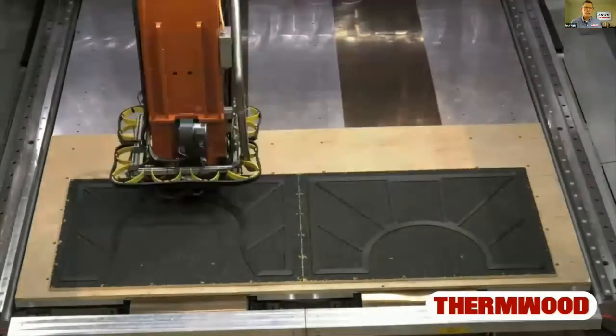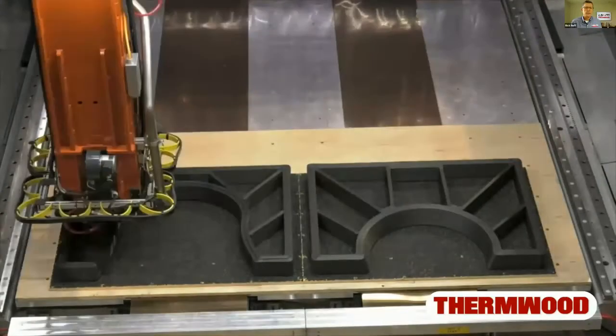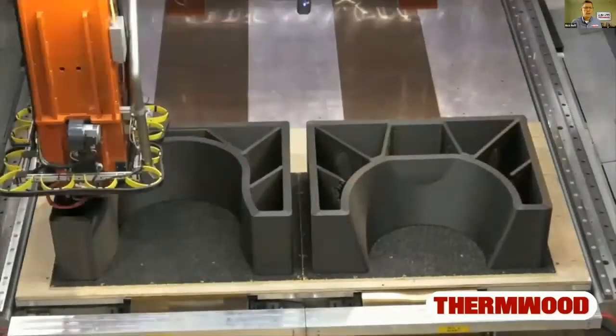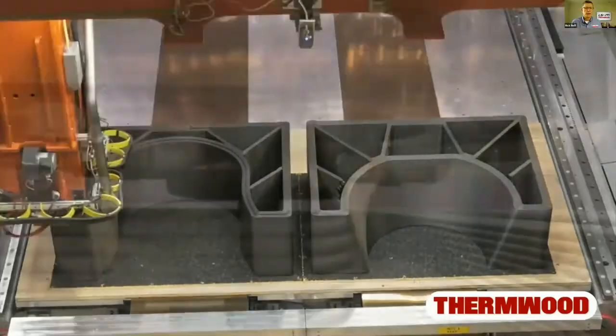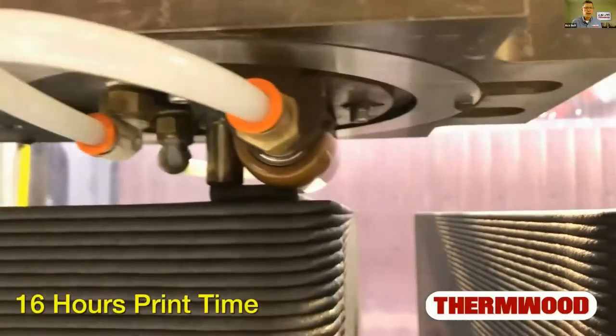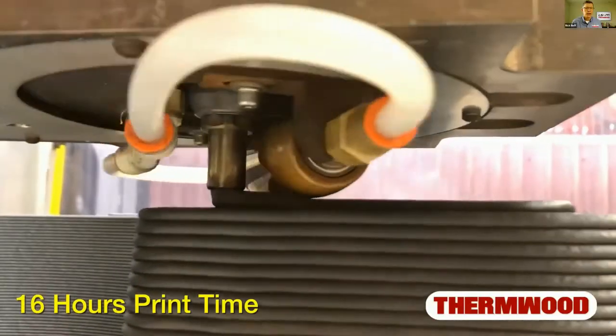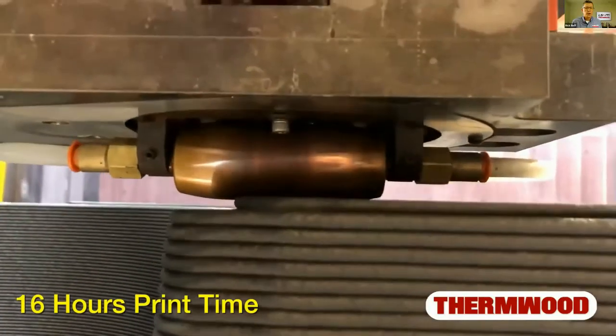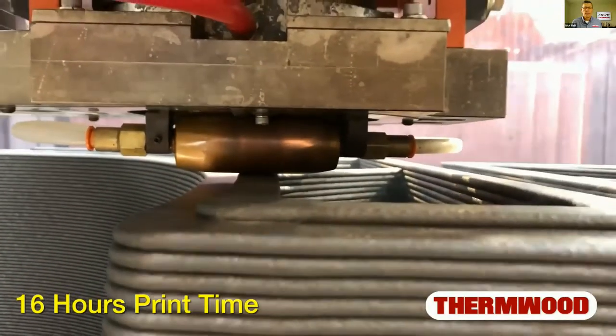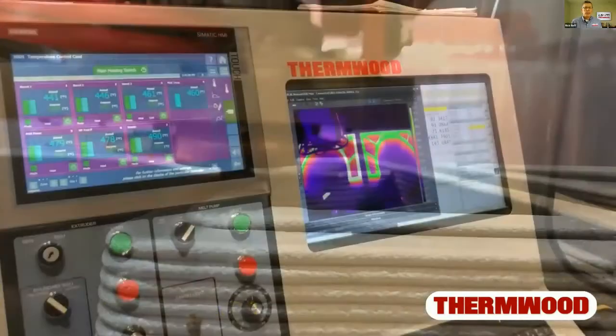And you can see that it was printed in two pieces. And the reason for that is you can print almost twice as fast because we can easily print two pieces in the proper amount of time for a single layer. So we print the entire part in about 16 hours. We can bond the two layers together.